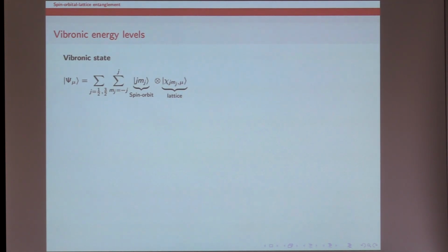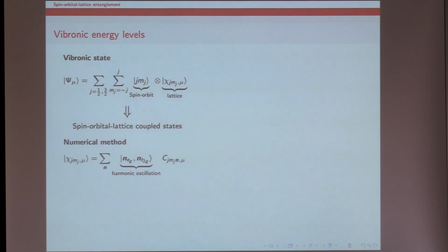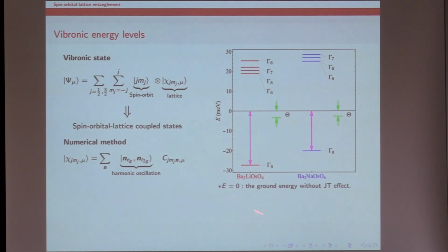The eigenstate of that Hamiltonian is expressed like here. This is a linear combination of the products of spin orbit coupled state and lattice degrees of freedom part. And so that's why we call this spin orbital lattice entangled state. And to obtain quantitative data, we did numerical calculation. To do this, this lattice part was expanded by using the eigenstates of harmonic oscillators. And then this is the energy spectra obtained by numerical calculation.